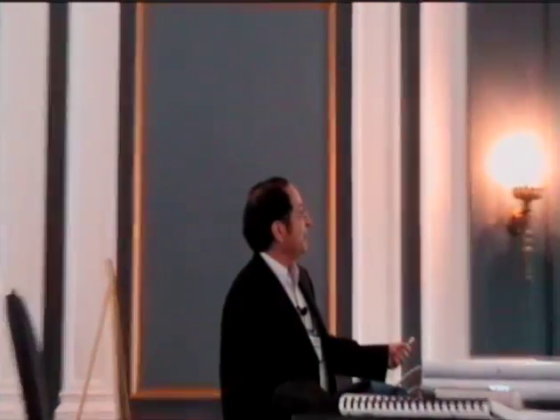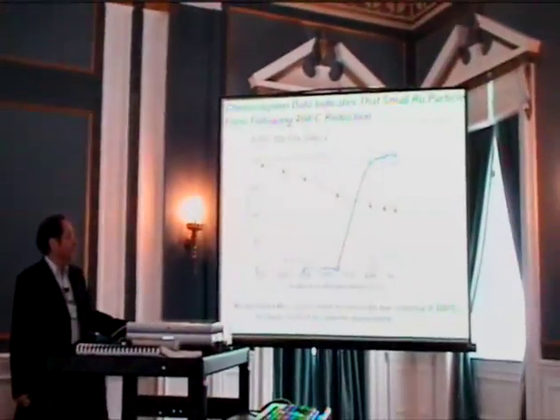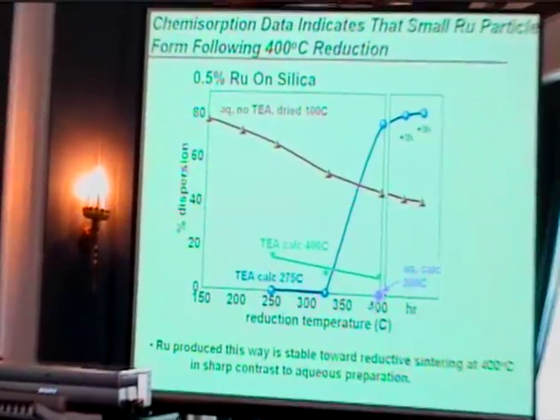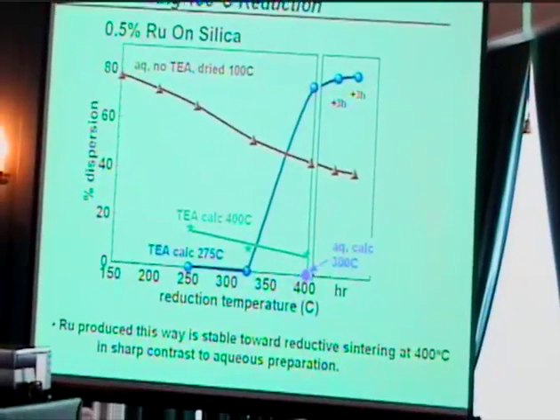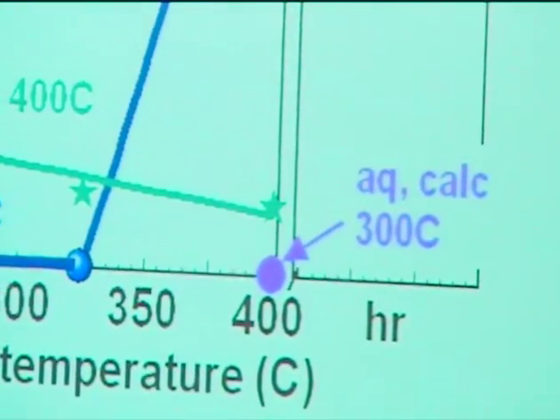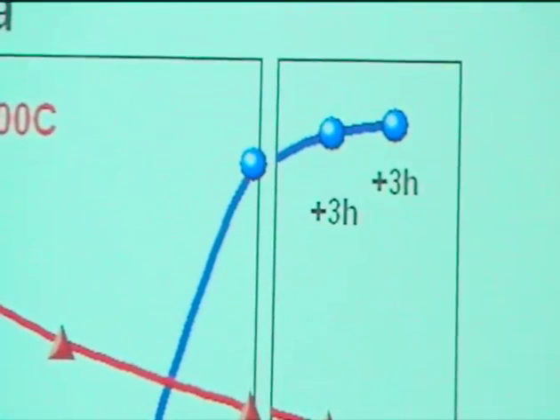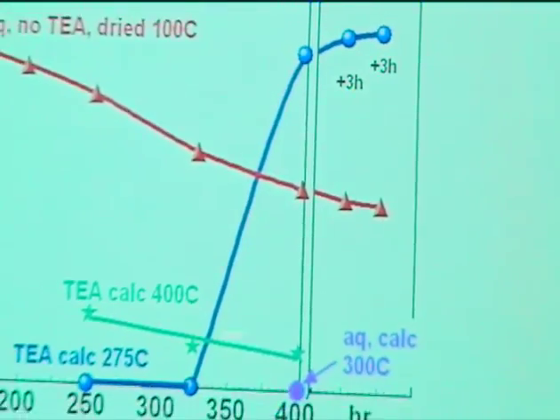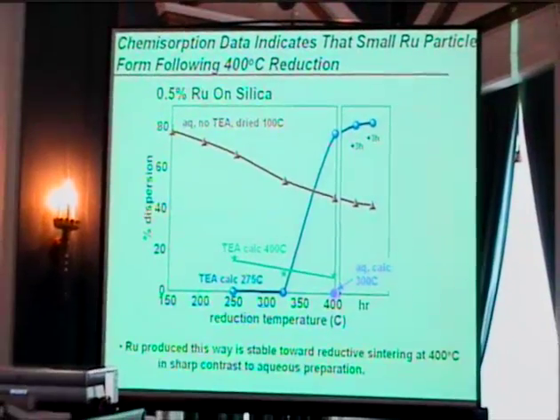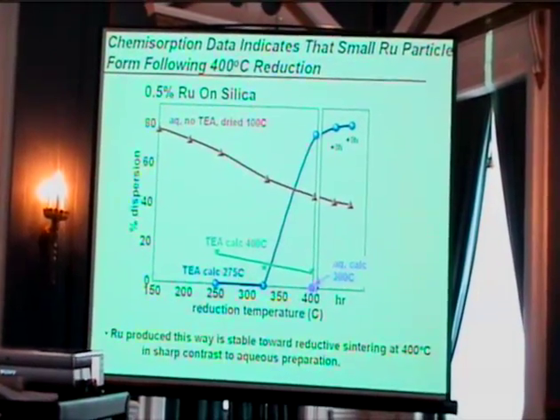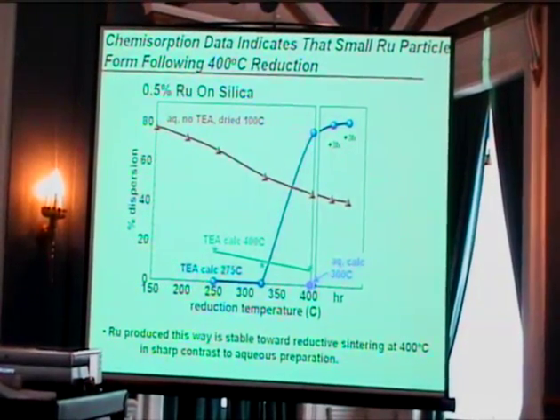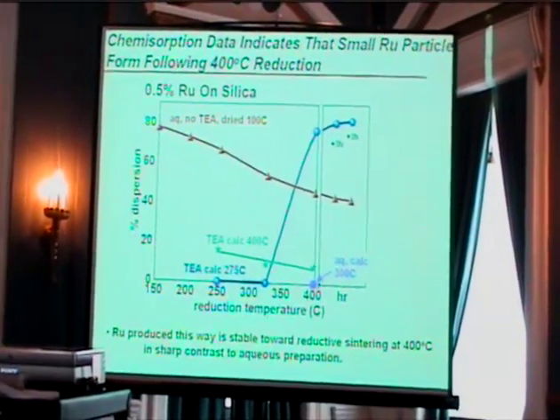It's an issue about site placement on a nanoscale structure. The corresponding samples that are much worse, if you actually take this aqueous one, you calcine it, so you get to ruthenium oxide, and then you go ahead and just reduce it to 400, calcine it at 300, and then reduce it to 400, you can barely measure anything. If you take this complex and calcine the complex away, it's obviously much lower than over here, but you do get a non-zero value, and that's also a reflection of what I'm going to show you of what's going on here. Okay, main thing is we've got reductive sintering, resistance to reductive sintering when we go through this complex.